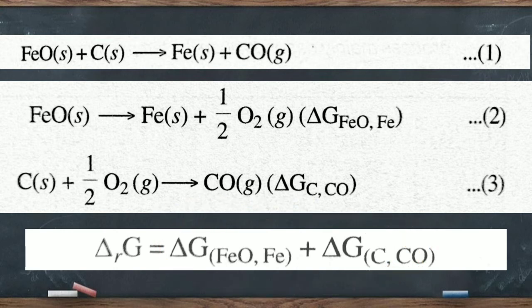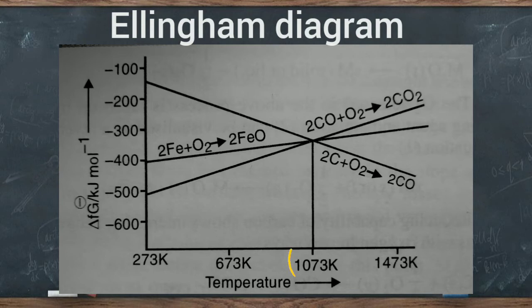The resultant reaction, that is equation 1, will take place only if the change in Gibbs free energy for the reaction is negative. We can find the approximate temperature for the reduction of iron oxide to iron with the help of the Ellingham diagram. At approximately 1073 Kelvin or above, the carbon to carbon monoxide line is much below the iron to iron oxide line. This means that delta G for iron to iron oxide is larger than delta G for carbon to carbon monoxide, and hence the change in Gibbs free energy for the reaction is negative. So we can say that at 1073 Kelvin or above, coke will reduce ferrous oxide to iron and itself will be oxidized to carbon monoxide.